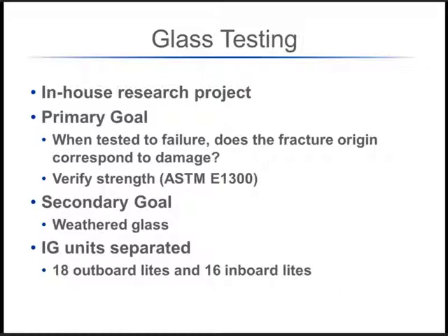your guide for that. So clearly, the nice part about this is that because it was in-house research, we were verifying the strength based on the current version of E1300. Obviously, we don't know what the strength of the glass was that day when it was put in about 20-some years ago, but at least we could verify the strength to see if it met what E1300 would say today. And E1300 is originally based on thousands of glass lites that had been tested by another glass fabricator, but they've been based on annealed glass.